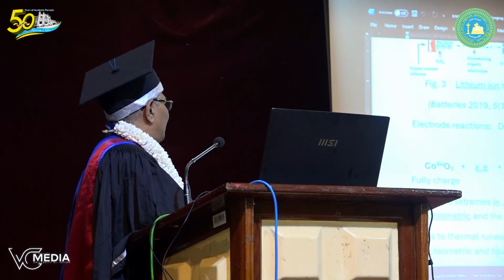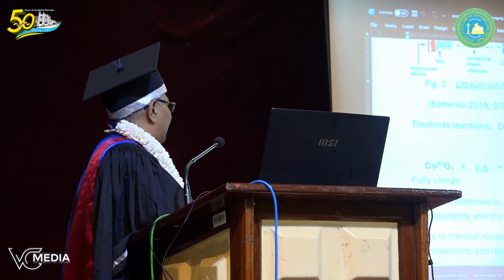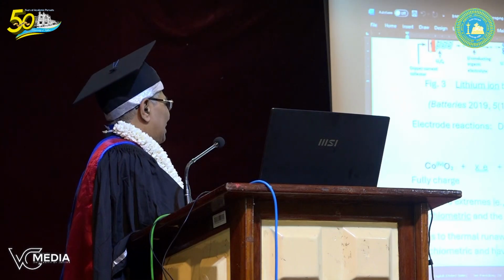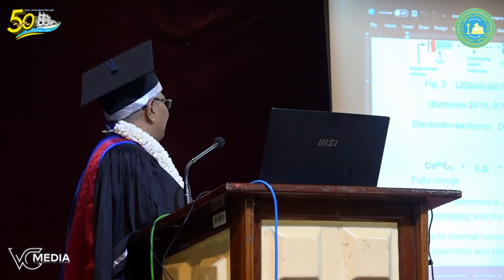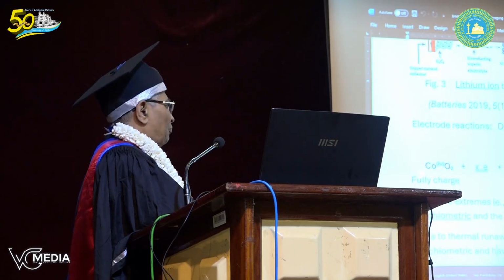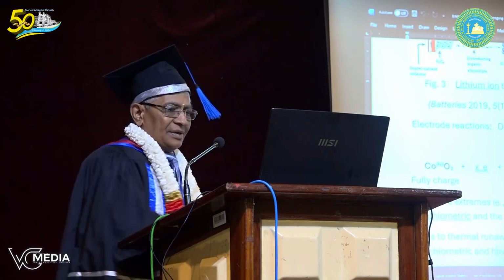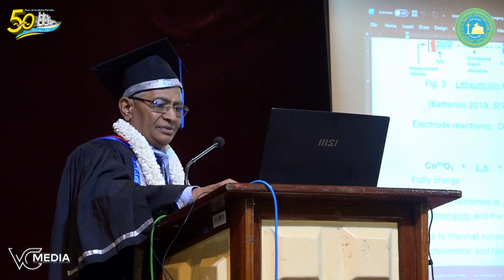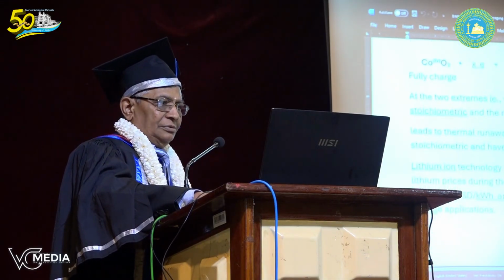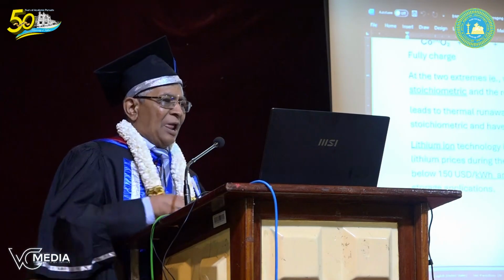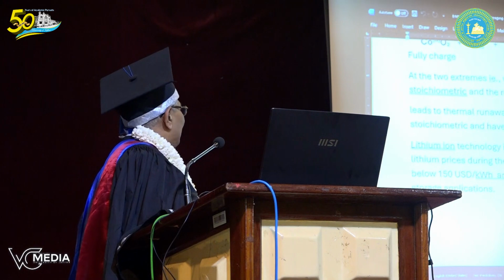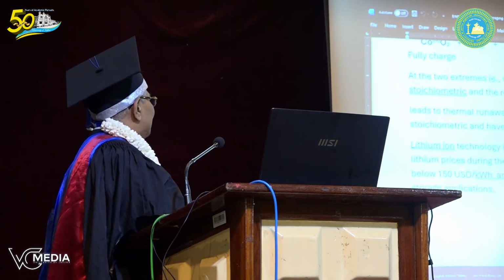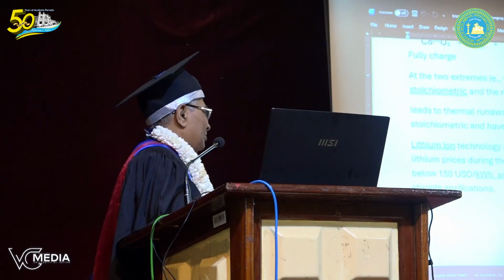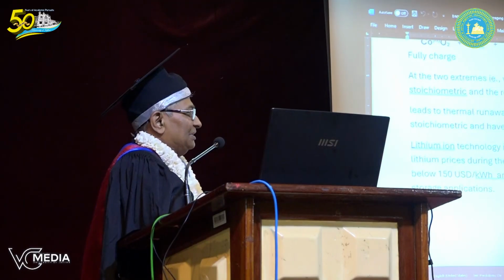And so these are non-stoichiometric compounds, and when it is fully discharged, cobalt will be all reduced from 4 to 3. So finally it ends up with lithium cobalt oxide with oxidation state 3, starting with cobalt in oxidation state 4 here. So that's what is happening, and there's an interesting reaction occurring, and that's why we got the Nobel Prize. And now lithium-ion technology is well developed, and there has been a tenfold reduction in lithium-ion prices during the last 10 to 12 years. Now, that's another point where actually the lithium-ion prices have come down.